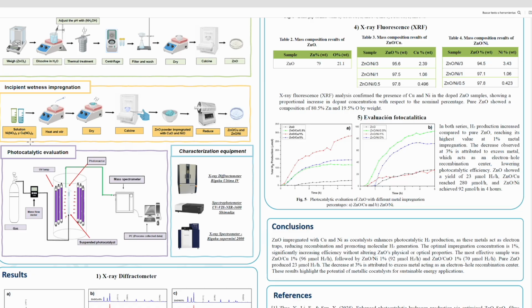And well, once we have the zinc oxide, we prepare our metallic salts with nitrate, cupric nitrate, and nickelous nitrate. And we proceed to prepare the solution by incipient wet impregnation. We let it dry, then calcine it, and here we obtain zinc oxide with copper oxide, nickel oxide, and then we proceed to reduce it and thus obtain our nanoparticles of reduced zinc oxide copper and zinc oxide nickel.